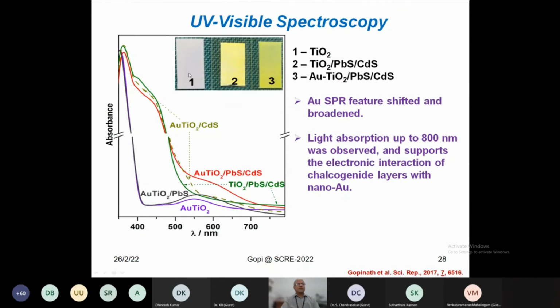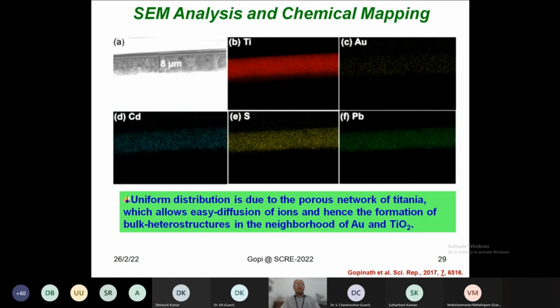So we made 3 photoanodes. One is pure titanium, which is given as 1, and the second is the same titanium layers with lead sulfide and cadmium sulfide assembled into the pores. The third one, which is slightly greenish yellow, is integrated with a small amount of gold. You can see the gold, titania, lead sulfide, cadmium sulfide, given as 3, whose UV-visible absorption is shown in red. It absorbs UV light, visible light, and a limited amount of near IR light also. When we look at the chemical distribution of all the elements, we can clearly see that in the thin film of about 8 micron, the lead sulfide and cadmium sulfide are uniformly distributed right from top to bottom. That means quantum dots are available in the pores for the entire 8 micron thickness.